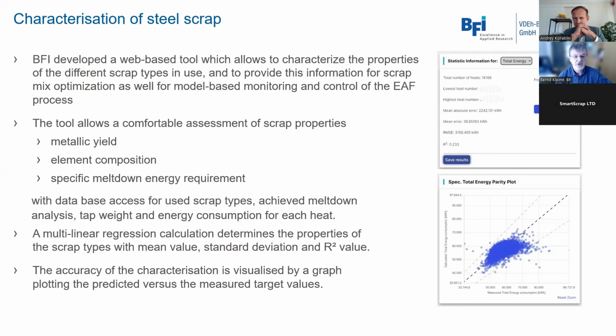And then the accuracy of the characterization is visualized by a graph. Here we plot the predicted versus the measured target values. Here you see an example for the electrical energy consumption. You see that the error of this prediction is quite small, and also the reliability is rather high. Of course, you always have some outliers here in the edges of this scattering dots for the different heats, but in the end, the result is quite reliable.